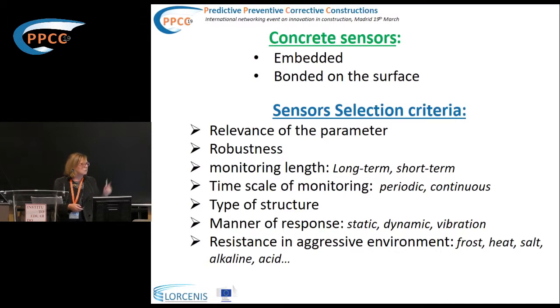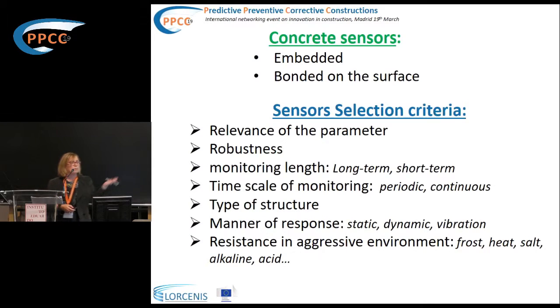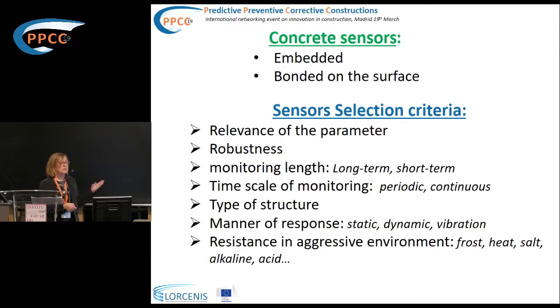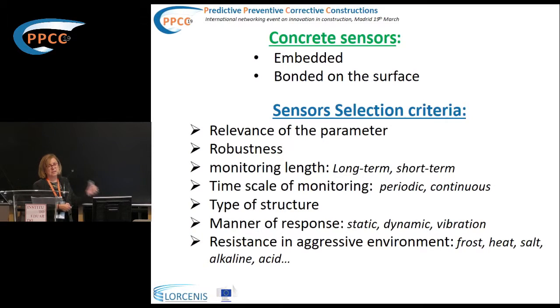Long-term means 120 years, as in one of the bridges mentioned previously. Or it could be short-term — for measuring how hydration is evolving and how strength is increasing in the structure. Or we may take measurements periodically by remote. The type of structure can condition the monitoring system a lot, including the manner of response — dynamic, static, vibration — and the resistance of the sensors to the aggressive environment, such as frost, heat, alkaline, or acid conditions.